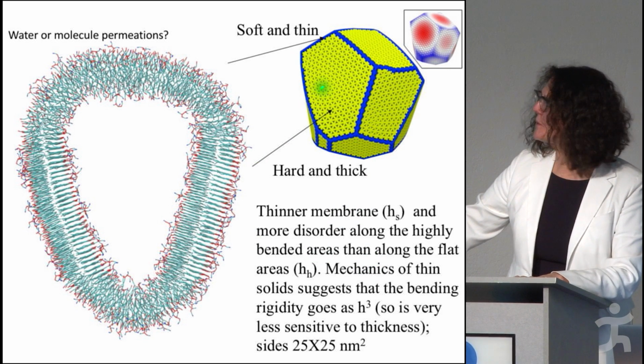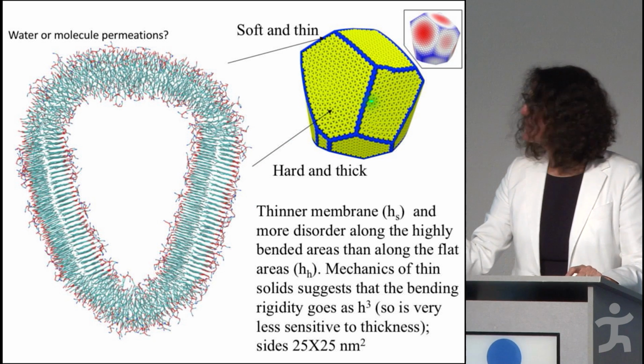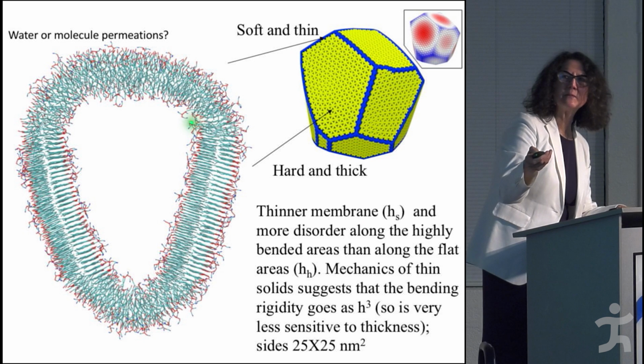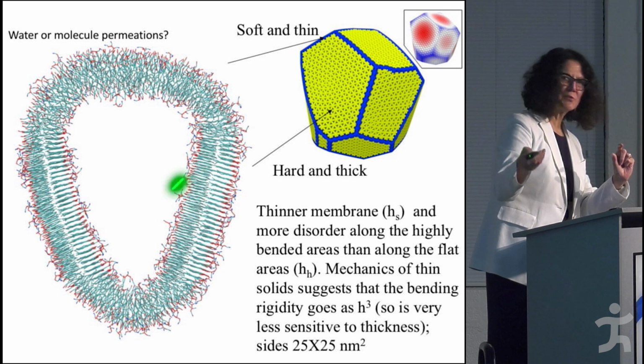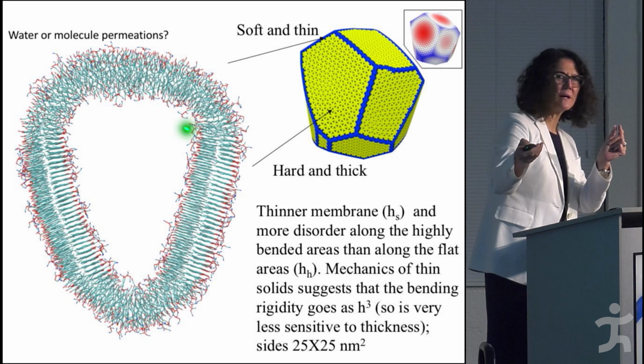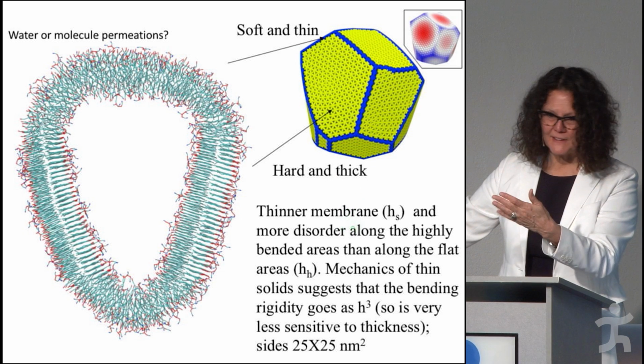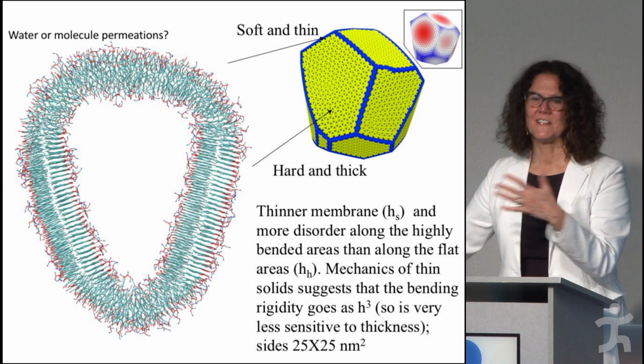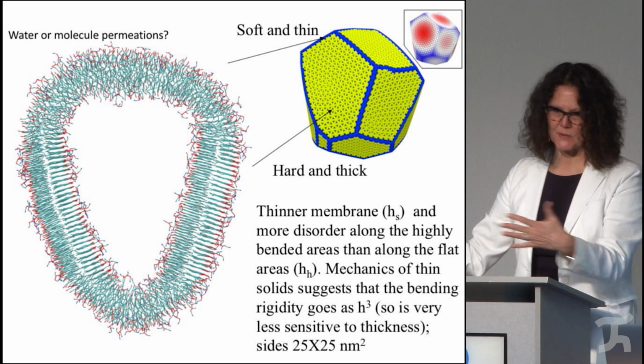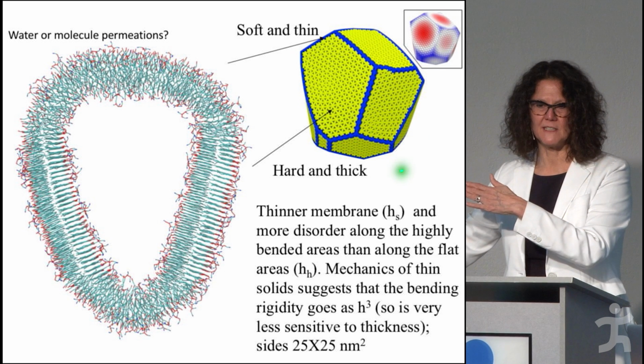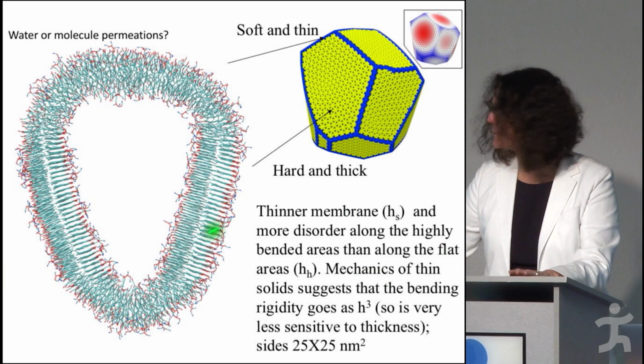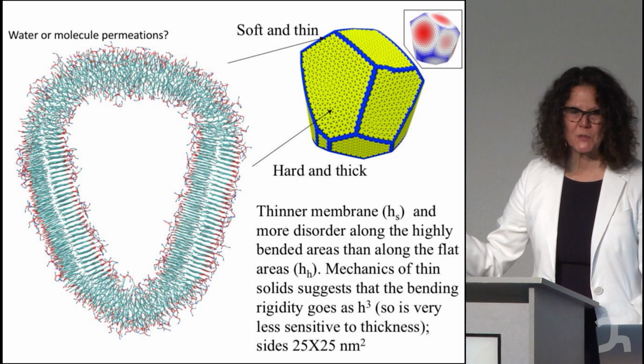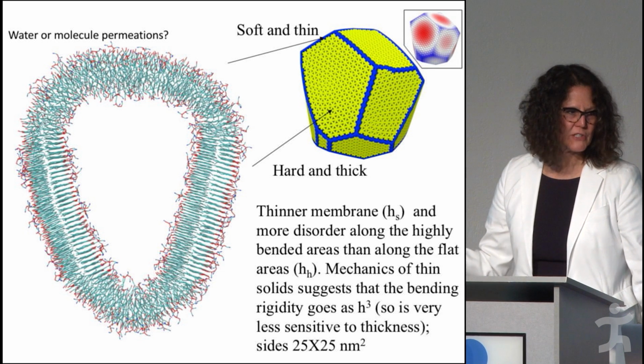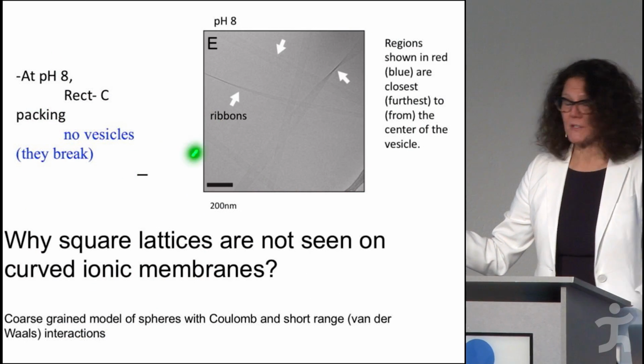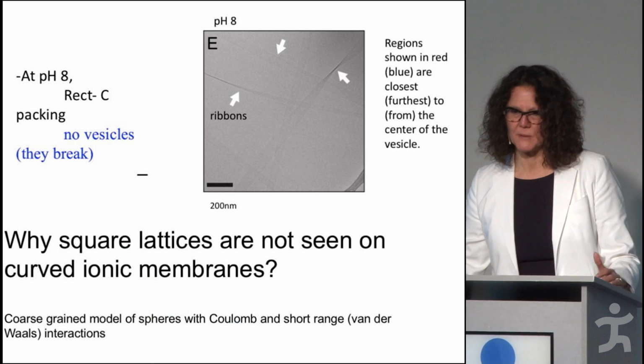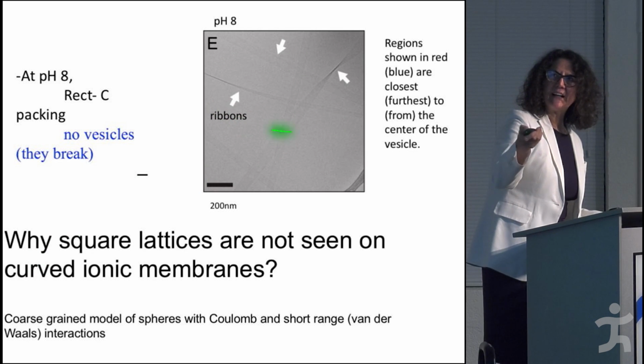But the interesting thing is I showed you the continuum model that has nothing to do with the molecular model, and it shows very similar results. If we just assume, for example, that here is thinner than this part, so this one is more rigid, just by continuum mechanics, than these parts, and then we put those parameters in the modeling, you get very similar shapes. Okay? So this is how everything will converge to the same sort of principle. But we predicted this by the continuum, and then we went back and designed the structures and showed that it does work. So this is a nice exercise of what you can do with soft matter and the tools we have now, computation and theory and so on. And of course, it needs the experimentalists that are willing to go and try this in the labs, because it was all done theoretically. So here are the ribbons that they break.